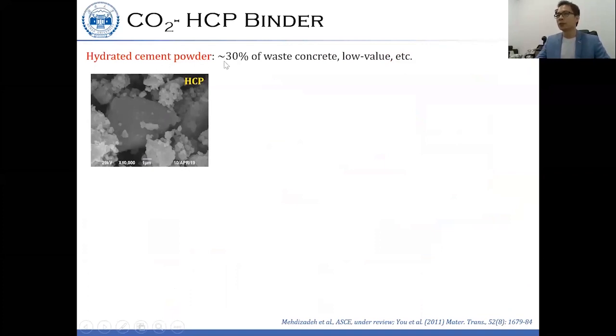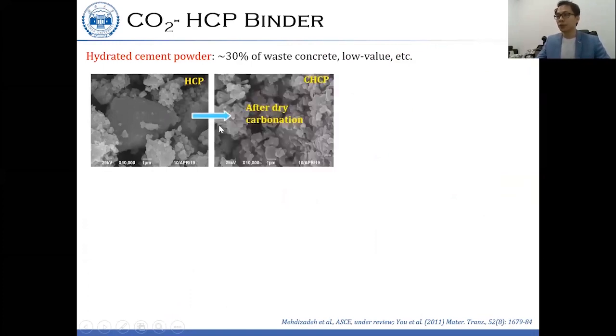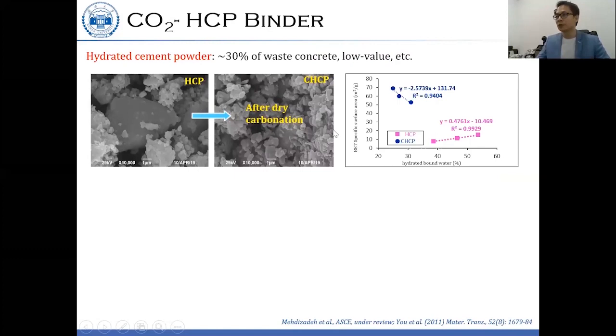In another study, we used hydrated cement powder, often called cement waste powder. It makes up 30% of waste concrete, and this material is actually regarded as very low value due to its high water absorption. Through the dry carbonation process, we found the formation of calcite around the particles. This in turn significantly increases the specific surface area and also decreases the hydrated bound water.